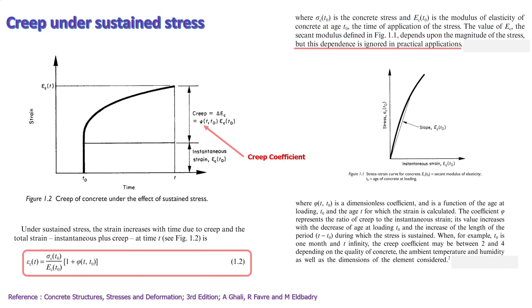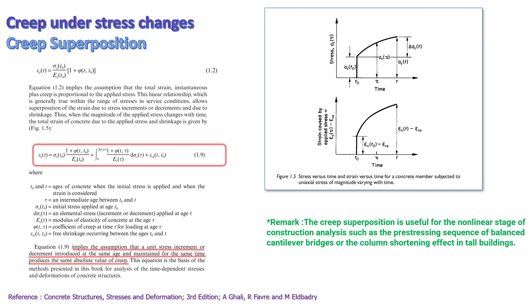The concrete creep behavior under constant stress could be expressed with this equation. Under sustained stress, the creep strain increases over time. The nonlinear part of concrete Young's modulus is ignored in practical application. The creep coefficient represents the ratio of creep to the instantaneous strain. Since the real pre-stressed concrete structure will be subjected to various stages of stress, the concrete creep behavior under stress that changes with time could be expressed by the creep superposition equation as shown here, with the assumption that a unit stress increment or decrement induced at the same age and maintained for the same time produces the same absolute value of creep.